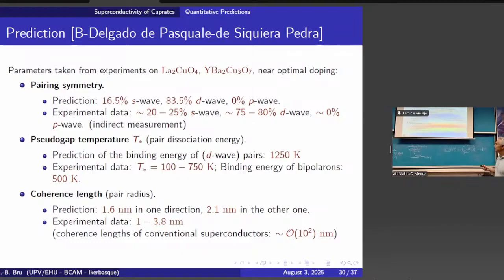And the more interesting thing is the coherence length. The prediction that we find is 1.6 nanometers in one direction, it's anisotropic, and 2.1 nanometers in the other one. And the experimental data is between 1 and 3.8. In fact, for a certain doping, optimal doping, it is 1.6, and there is another cuprate, which is doped not completely optimally, which gives you 2.1, exactly the same number, but okay.